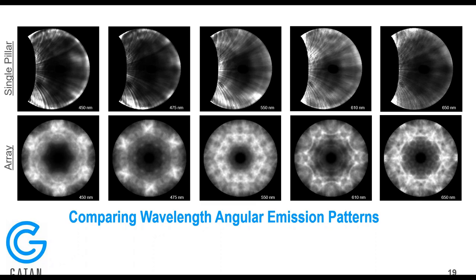What you'll notice is that the single pillar is missing a slice of angle space towards the left side. That's coming from the shape of the collection mirror, whereas for the array, that angle space has been covered up because, due to the symmetry, we were able to rotate the sample and fill in that angle space. So there's a few acquisitions that took place for the array case, and they were averaged together to give you this more full circular pattern.